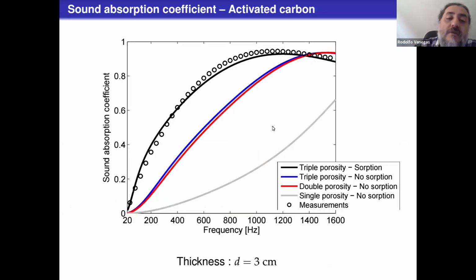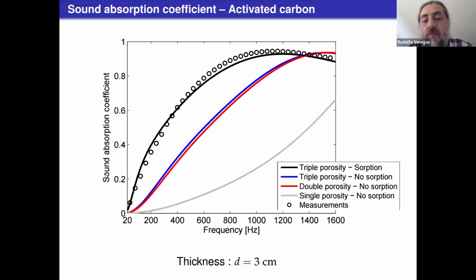coefficient. So the attenuation coefficient at low frequencies is much higher for a triple porosity sorptive material, and this is the experimental validation. In terms of sound absorption, which is a parameter that indicates that if it is equal to 1, all the sound energy is absorbed by the material, and if it is equal to 0, it means that all the energy is reflected back. When we consider this material placed on a rigid surface, we can see that the sound absorption coefficient is very high at low frequencies. If we compare it, for example, with a material with solid grains, like shown in gray here. So this is a remarkably high sound absorption for such a thin layer of 3 centimeters.